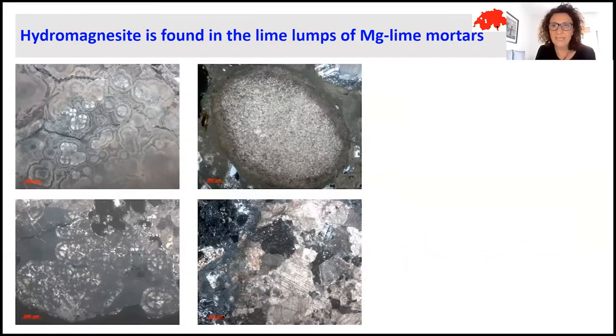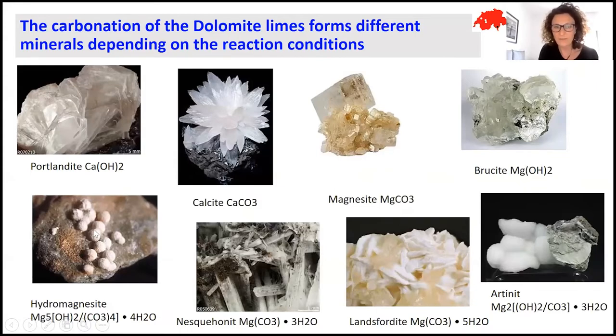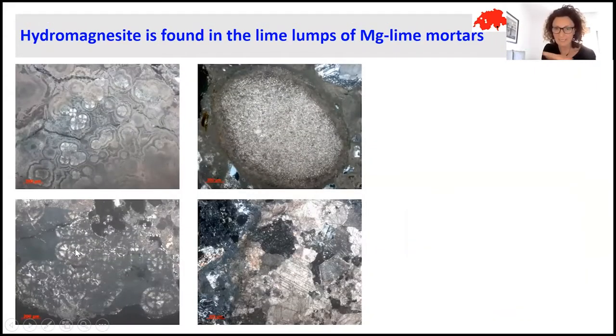I would like to present this case in order to show you which aspects a magnesium lime mortar has. It is possible, in some particular and lucky cases, I would say, to find this witness in lime lumps, this witness of hydromagnesite, which is not always formed or well visible, like in these cases. Just to show you briefly, this is the hydromagnesite mineral shape, and this is what I see while observing a thin section. So I can observe these radial and roundish shapes that testify to the presence of magnesium components.